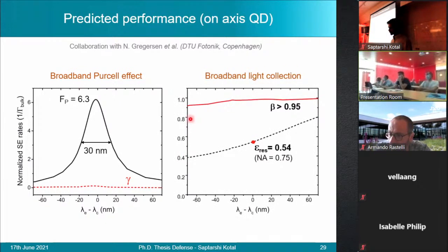We also observe that a nearly perfectly monomodal operation can be expected for a spectral range around 100 nanometers wide, with beta exceeding 0.95. Again, at resonance, we anticipate a collection efficiency of the order of 0.54 for a collection lens with a numerical aperture of 0.75.